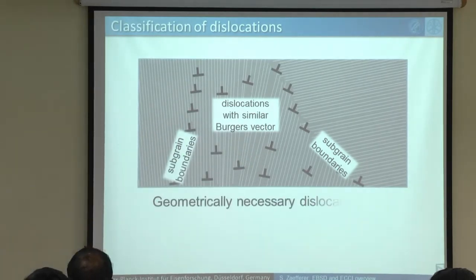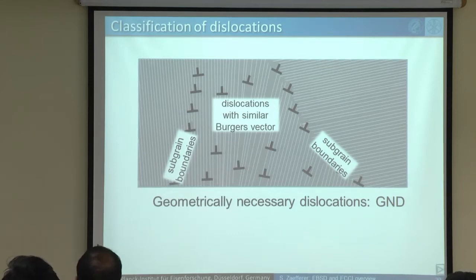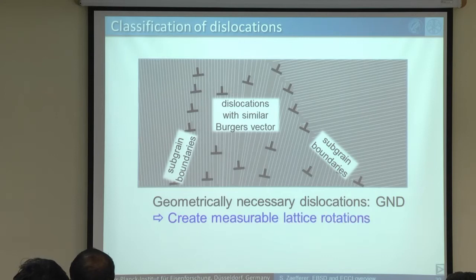So all these dislocations which make measurable crystal rotations, so a crystal rotation from here to here, from here to here, and from here to here, these are called geometrically necessary dislocations, because if you anneal this material and it's not recrystallizing, these dislocations will stay inside and nothing will happen. So they are measurable by EBSD, and we call them GNDs.